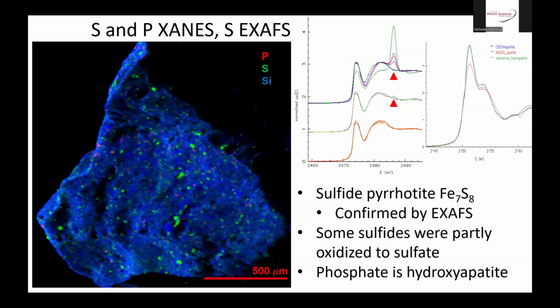And the last one, the phosphate. All of the phosphate spots measured in this sample matched apatite, the distinctive shoulder peak for a calcium phosphate. Match there. And for phosphates, you definitely have an issue with self-absorption. So the difference in the height of those peaks is some degree of self-absorption. Actually, in the standard, not in the... No, it's in one of the samples, not the standard. So you have to be careful of self-absorption.